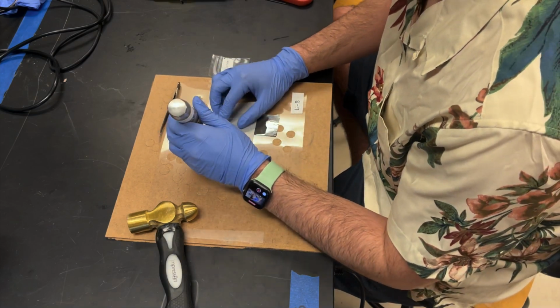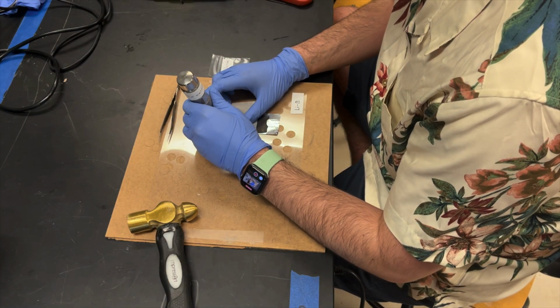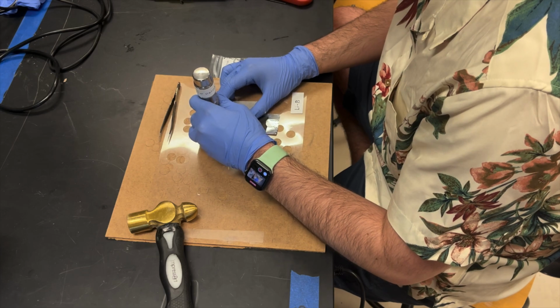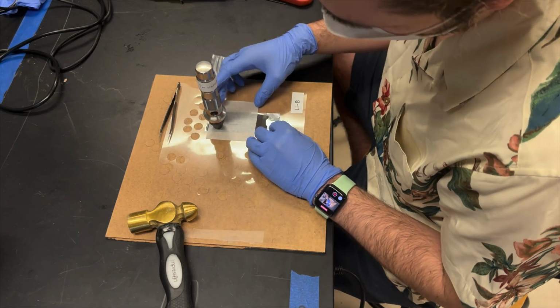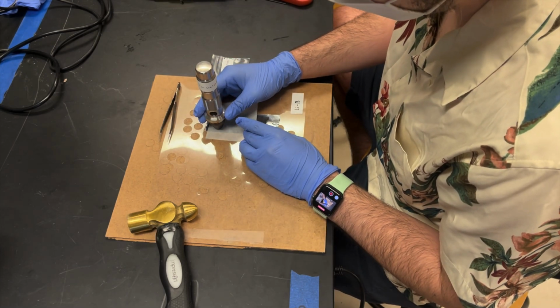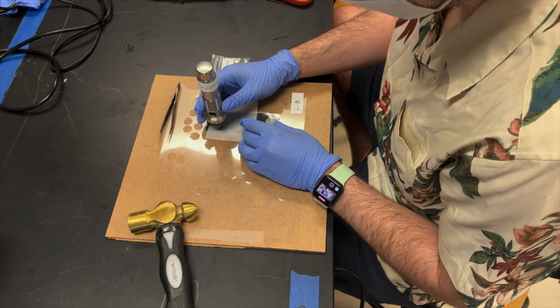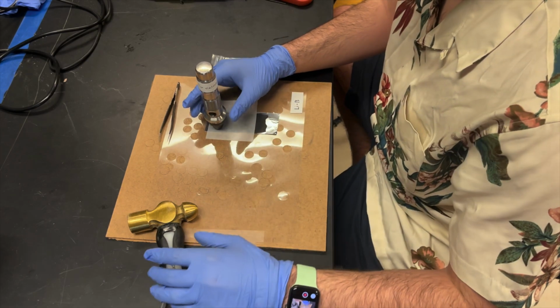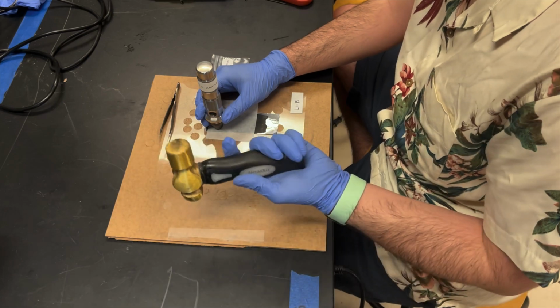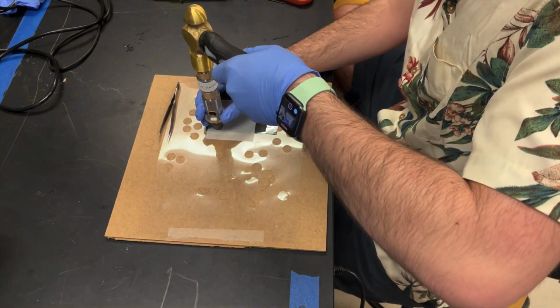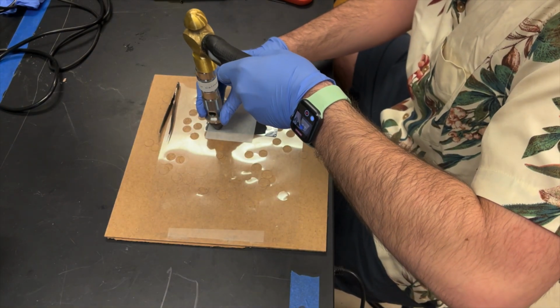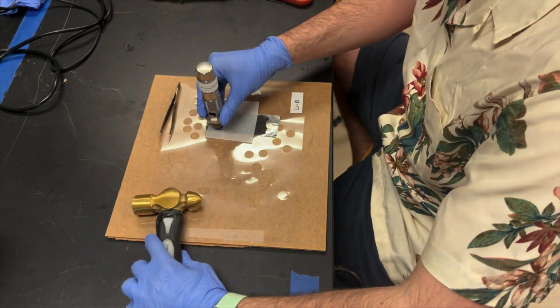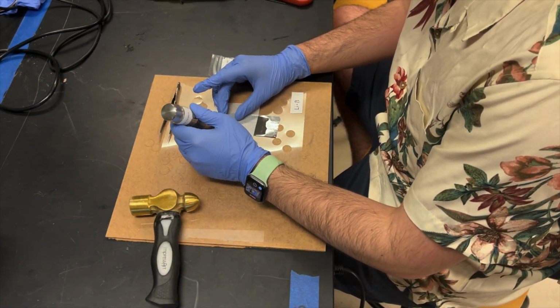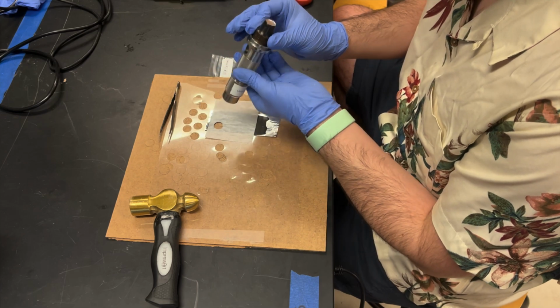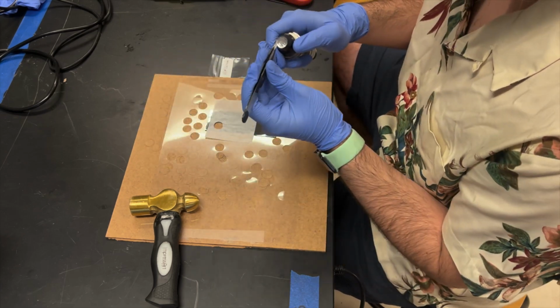We will also cover the foil with weigh paper so as to preserve the integrity of the punched disc and prevent cross-contamination. We will examine the foil for an area that is homogeneous and smooth as can be, then align the disc puncher. With one solid hit from the mallet, we will punch out the disc. The electrode will be sandwiched by discs of plastic and weigh paper and can be extracted with tweezers and placed into a small bag.